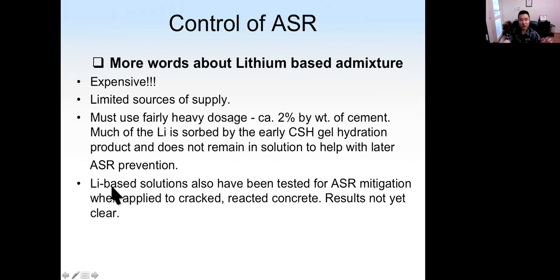Okay, and lithium-based solutions can also be used for ASR mitigation. That means when we already have ASR in concrete, if we apply the lithium-based solution, that may change the gel into a non-expansive nature, but the result may not be very clear. So depending on the situations. But anyway, lithium-based solution may be used if we already have ASR cracking in concrete.